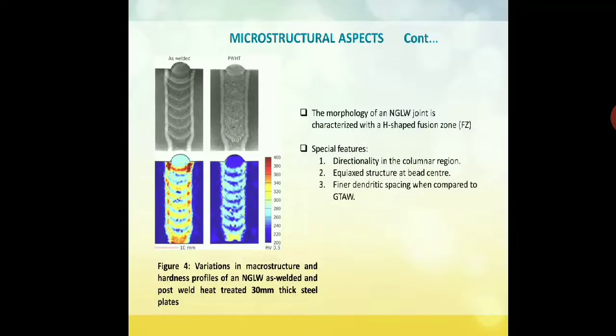The morphology of an NGLW joint is characterized by a H-shaped fusion zone. The fusion zone in the steels mostly consists of martensite phase in both tempered and untempered states, along with the presence of other phases such as ferrite, retained austenite, and carbides also. It all depends on the filler material and parent material combination, and also on the thermal cycles experienced during welding. The NGLW technique exhibits a special directionality in the columnar region of the weld bead with an equiaxial region in the center.